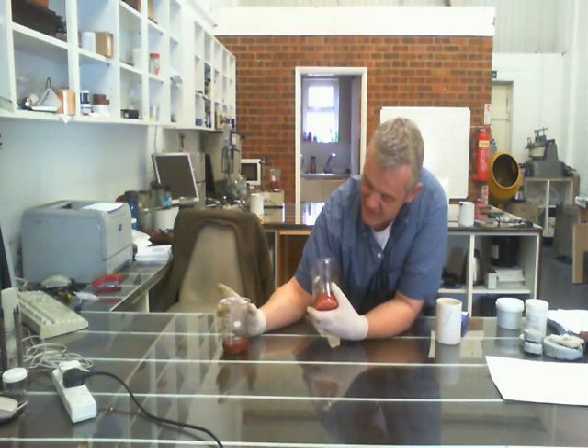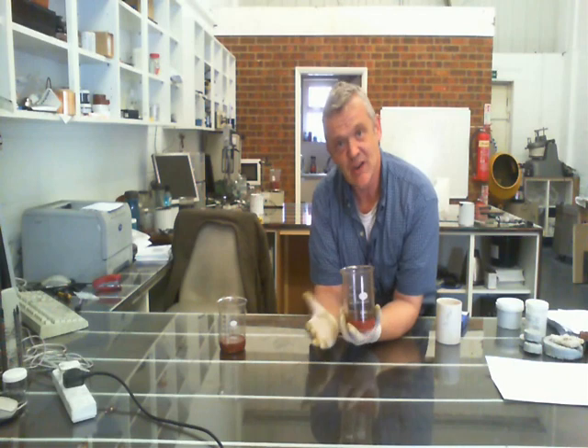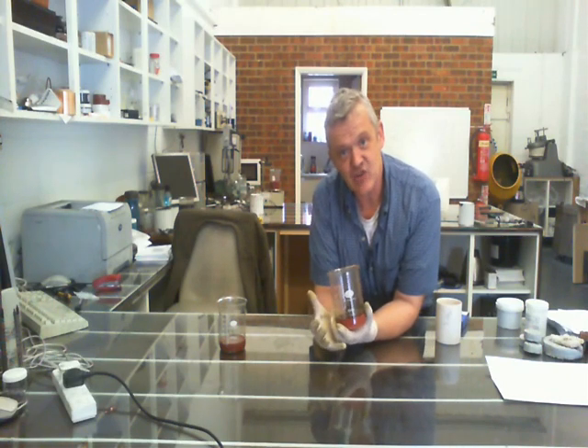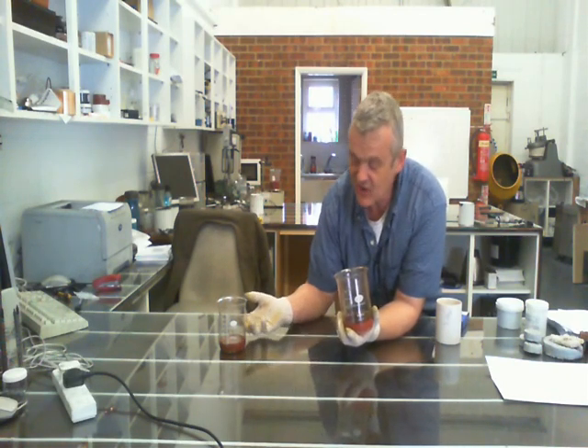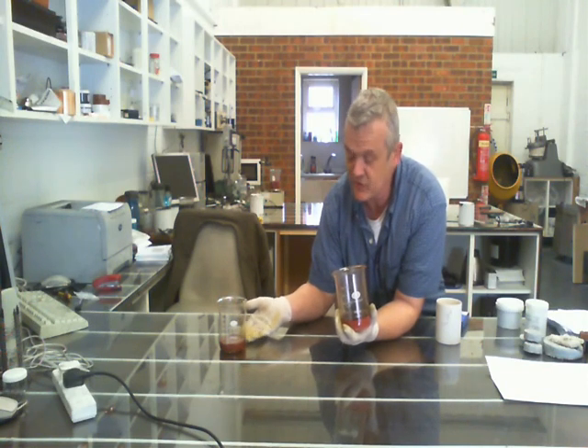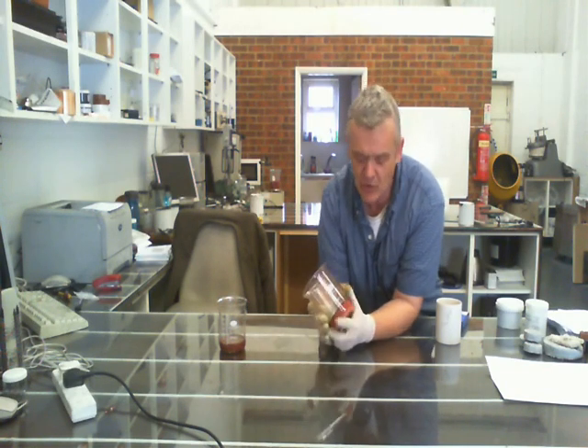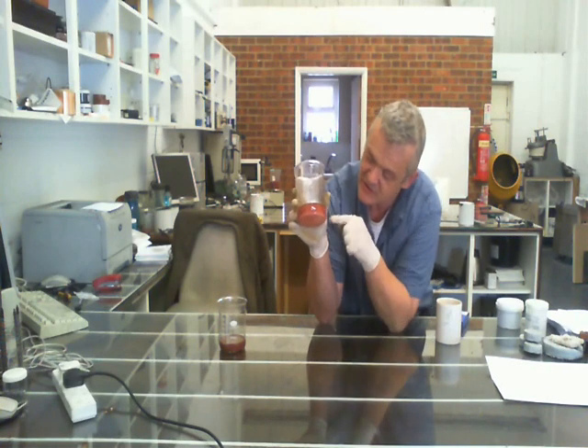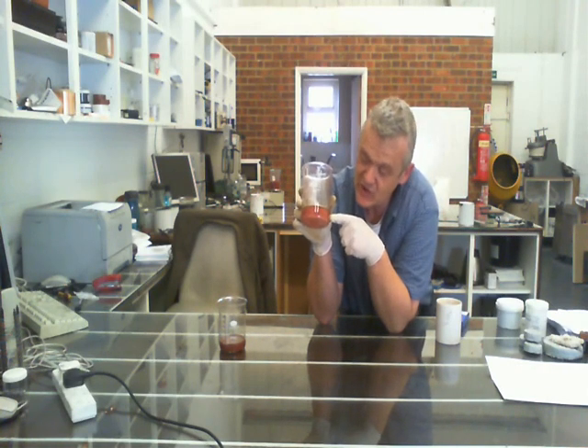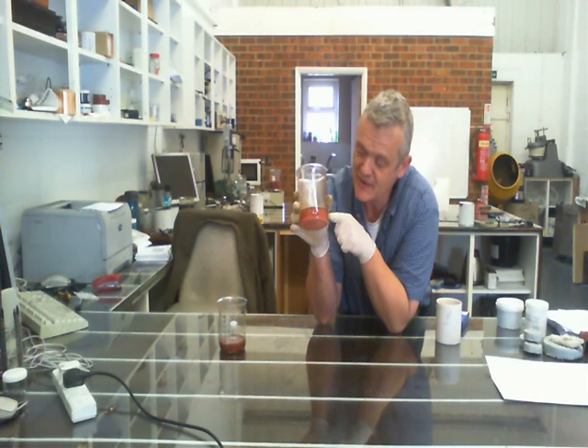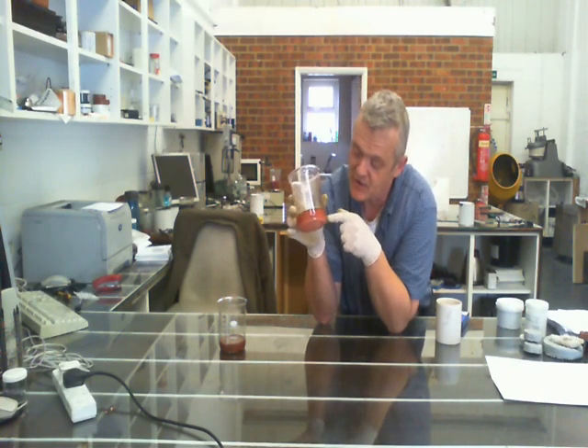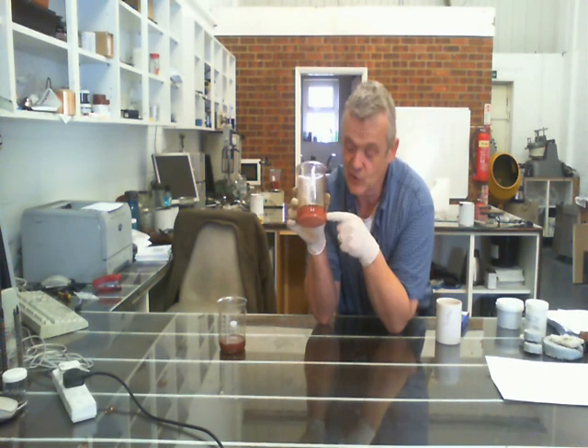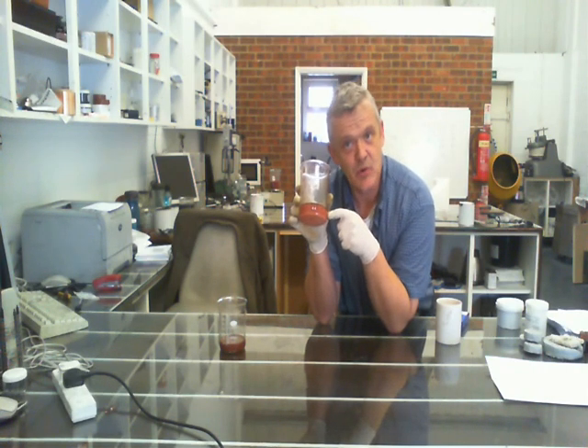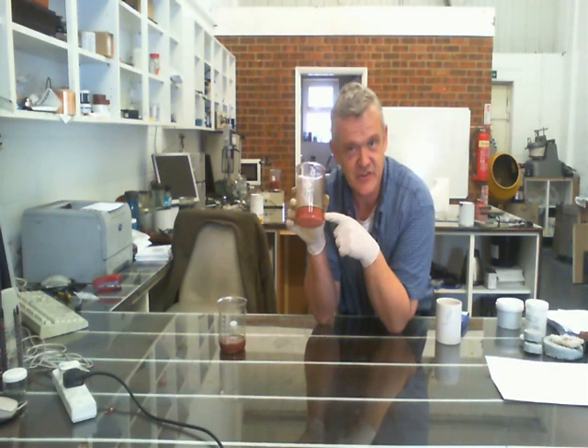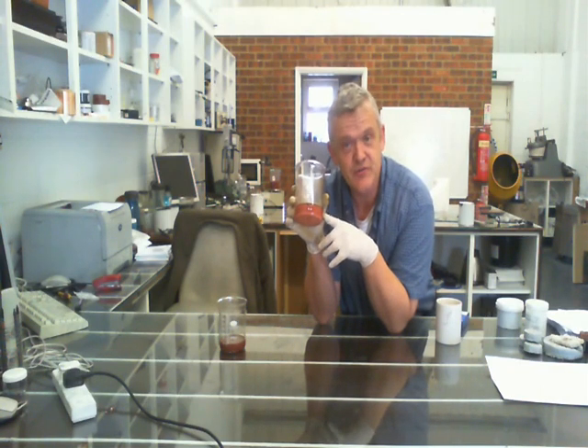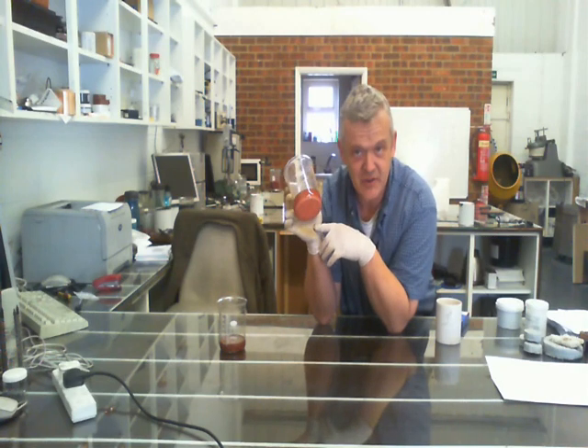Now, as you leave that, you need to leave that at about 50 degrees, because if you leave it cooler, the gelatin will set. And what you want to happen is the large particles sink to the bottom, the medium-weight particles stay in the centre, and the lightweight particles go to the top, which is exactly what's happened here. So this centre layer here has medium-sized gelatin-coated, water-dispersible copper nanoparticles already in a bit of copper formate for a photosintering copper ink. That will mix up quite well with water and a binder system, a carrier system, and make good photosintering ink with copper nanoparticles in it.